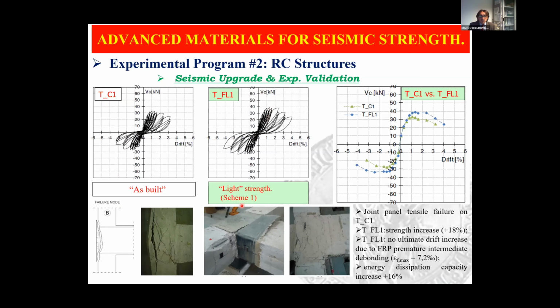This is the behavior of the specimens strengthened with FRP in the light scheme, and we are comparing the results in terms of shear recorded in the column versus drift. And here you can see the envelope of these two behaviors for control and strengthened specimen. As you can see, the strengthening solution allowed to increase the strength capacity by 18%, but no ultimate drift increase was achieved due to premature debonding of FRP. And this is because we just used one layer and the anchors were not able to prevent the debonding. But in any case, we achieved a good energy dissipation, which was 16%.